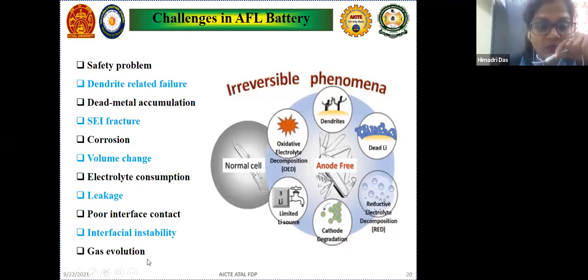Here I have mentioned a few of the real challenges in the anode free battery, like SEI fracture, corrosion, and volume change. Here is the point about corrosion: because the anode free current collector is bare copper, the corrosion of the current collector is very visible in the anode free battery, and on this copper layer there will be accumulation of dead lithium. And similar things like leakage, poor interfacial stability and interface connection, and gas evolution will happen in anode free lithium ion batteries.